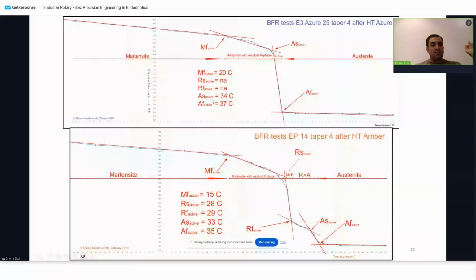Here, to start the austenite phase, it will be at 34, and the highest temperature to impact the austenitic phase is 37. But in Easy Pass, we use a method of heat treatment where the impact will be higher, at 35. So it means that you need to cool down the Easy Pass file for many reasons more than the Azure. The Azure can take more stress and more heat generation than the Easy Pass. Okay, so as a simple no-brainer, this file has a smaller taper and this file has a bigger taper. Overheating will impact this one more than this one.